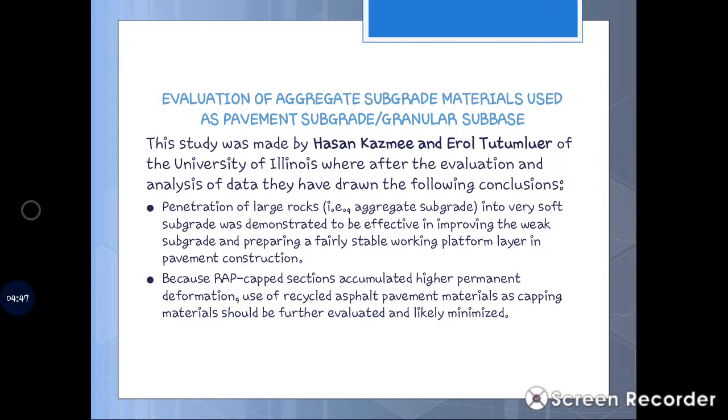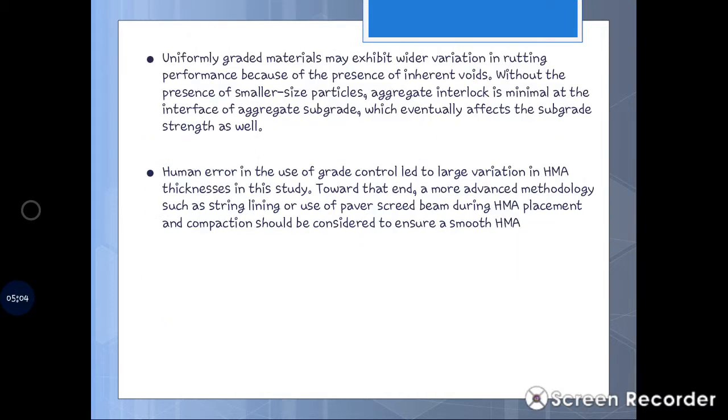And because RAP or recycled asphalt pavement cap section accumulated higher permanent deformation, use of recycled asphalt pavement materials as capping materials should be further evaluated and likely minimized.